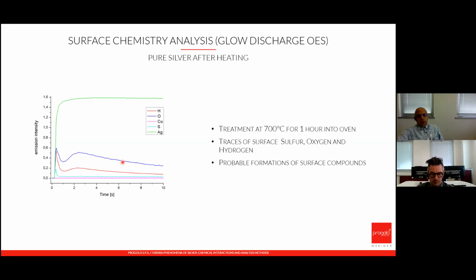The thermoxidation of pure silver probably led to the surface formation of silver compounds more complex than simple oxides, because they are thermally unstable, as I told you before, over 200 Celsius. So with the likely formation of much more stable silver sulfates, the higher oxygen content under the surface may depend on the strong diffusivity of this gas over 400 Celsius. All of us know the incredible capacity of silver to dissolve extraordinary amounts of oxygen, especially in the molten state.